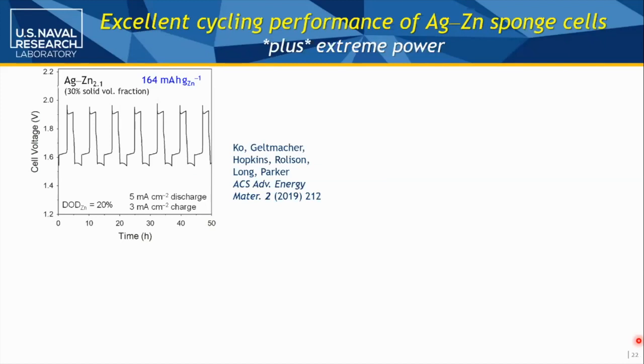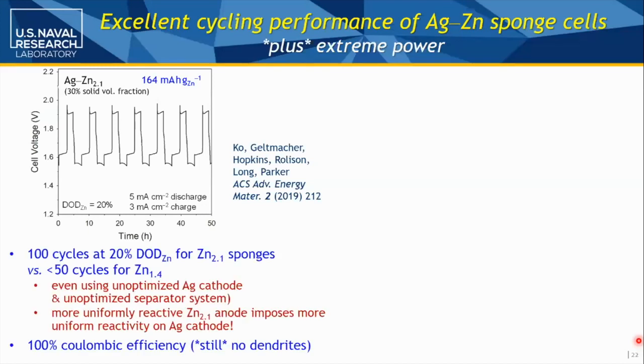The other thing we noticed with this more dense sponge, 30% of the sponge being zinc versus the silver, is we could now get 100 cycles, and we were doing nothing to optimize the separator system and the silver cathode, which you need to do to even get tens of cycles. Our zinc Gen 1, the 1.4 grams per cc, would give us 50 cycles without a problem. We were doing 100 with the new version.